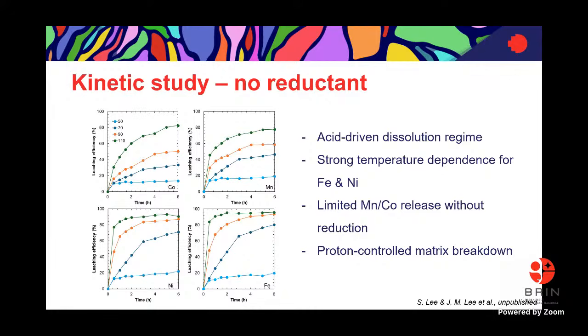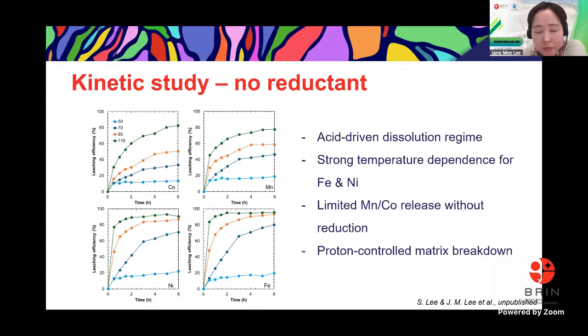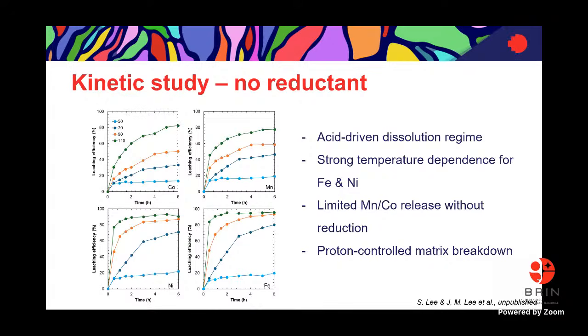And NiO maybe will bond the acid and make the nickel salt, so we can easily get the nickel ion, I think. But in your process, you only use 110 degrees Celsius for 6 hours. Can you explain to me, at such a very low temperature, why you can successfully leach so much nickel, up to 85% nickel recovery? Thank you.